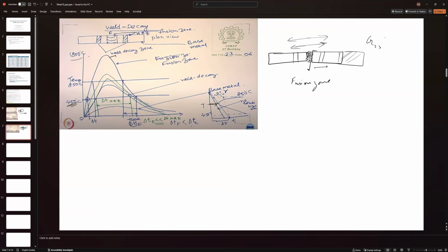Cr23C6 is unstable above 1200 degrees Celsius. Above 1200 degrees Celsius, it dissolves. So we don't have precipitates at the grain boundary, and we won't get IGC.